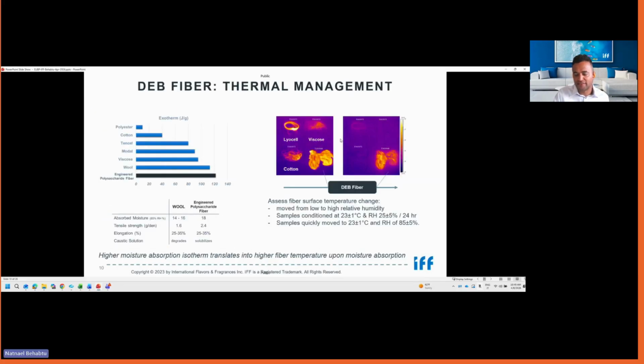So just one last slide about the performance of this material. It is a polysaccharide, so it tends to manage moisture. But again, I was telling you at the beginning, slight changes in the stereochemistry of the linkage can make a big impact in this polysaccharide. So specifically here, what we are showing is the exotherm, so basically the heat associated as moisture is absorbed. Clearly, polyester is fairly poor. It doesn't absorb moisture. It makes sense.